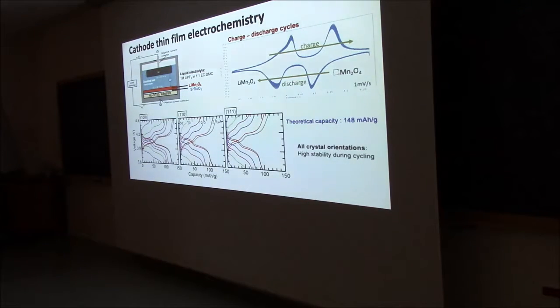Of course, if you change something in the structure, you do with doping, you can do that a little bit. But you're in this range of 4 volts. So for instance, if we replace part of the manganese with nickel, we go from 4 more towards 5 volts. Which some people do, because you can put more energy in there. But there are other issues there.